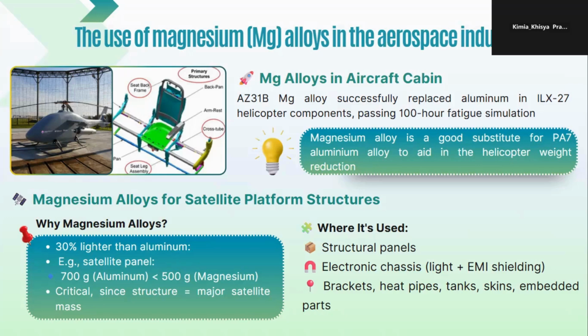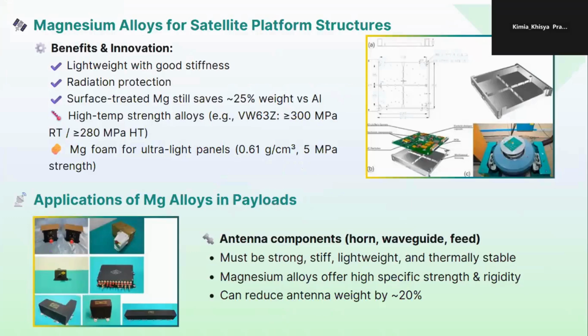tanks, skins, embedded parts. And the benefit of using magnesium alloy for satellite platform structure is that it is lightweight with good stiffness and radiation protection, and surface treated magnesium still saves about 25% weight versus aluminum. This magnesium is a high temperature strength alloy, and magnesium foam for ultralight panels is about 0.61 gram per cc and 5 MPa strength.